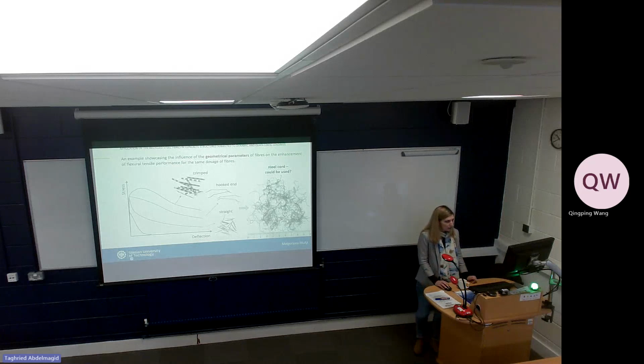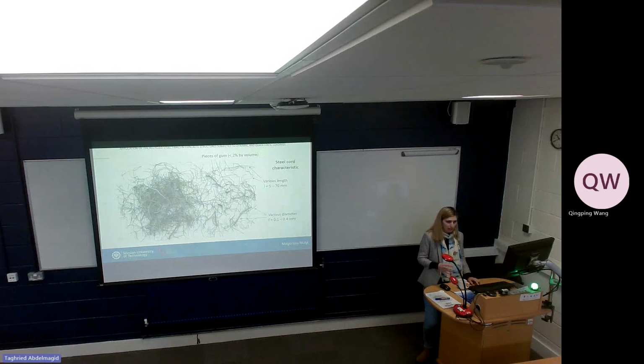Of course, the best increase of strength is observed when we use the longer fibers. The longer the fiber, the bigger the increase of strength. And when we put the longer fiber, then we have a lower number of fibers per square meter. So here it is the opposite. We have a lot of fibers. So this can be an advantage and a disadvantage.